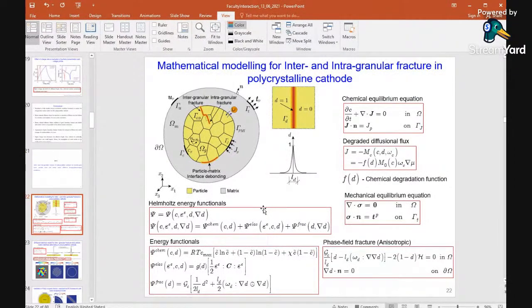We take a polycrystalline structure which is surrounded by a matrix, and here we include both intergranular fracture and intragranular fracture. So the crack can enter through the grain itself, which was not there in the previous model. In this case, we consider a diffuse fracture model instead of considering the grain boundaries as a distinct interface. So we diffuse the grain boundaries in this model. D is the parameter which tells whether the interface is cracked or not. D equals 0 means intact, and D equals 1 is the crack.